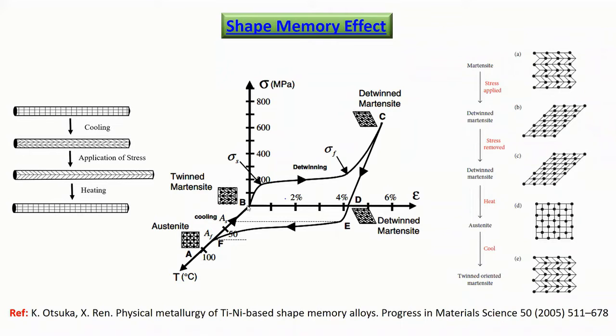Okay, and on that twinned martensite, if we are applying stress, then this is what is happening. It is going through detwinning, as I said, the stretching of the twins, and that leads to some amount of strain. This detwinned martensite can deform elastically, and when we are unloading, it is coming back to the same form, the detwinned martensite here, okay?